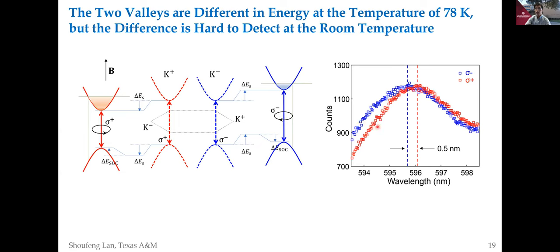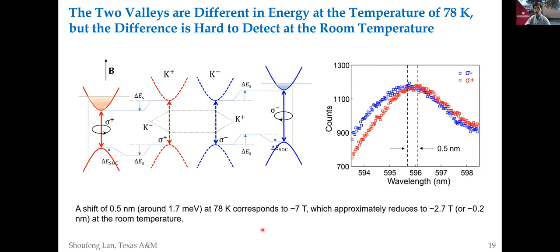During the experiment, indeed, we observed a spectral shift of around 0.5 nanometers between the PL emissions, sigma minus and sigma plus. This 0.5 nanometers corresponds to a magnetic field of around 7 Tesla, and this is at the temperature of 78 Kelvin. And we know from the Bloch theory about the ferromagnetism's dependence on temperature that the field of around 7 Tesla will further reduce to 2.7 Tesla at room temperature, which corresponds to 0.2 nanometers. It's very hard to measure such a small difference in the PL spectrum at room temperature, not to mention that there's significant thermal broadening at room temperature.